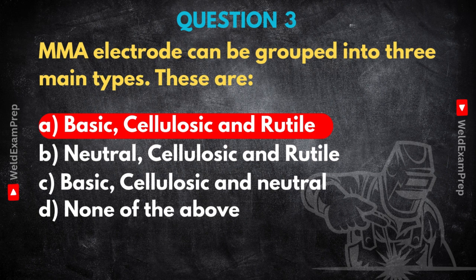And finally, rutile. These are generally seen as the easiest to use. Smooth arc, nice looking bead, slag comes off easily, great for general fabrication, maybe where appearance matters more, often liked by learners. They don't penetrate like cellulosic or have the low hydrogen of basic, but for ease of use and looks, they're good. An inspector might check these welds carefully for slag inclusions, though. If the slag isn't cleaned properly between passes, it gets trapped, and that's a defect. So yeah, each type has its place. Understanding that place helps you judge if the right consumable is being used and check for the relevant quality issues.